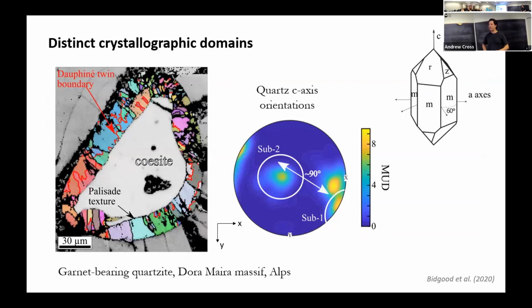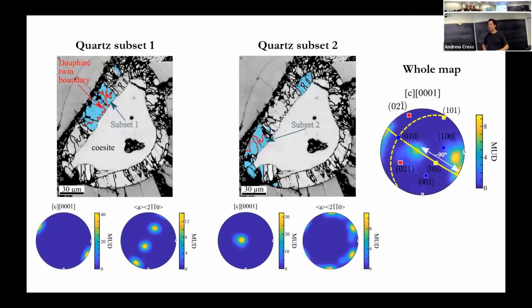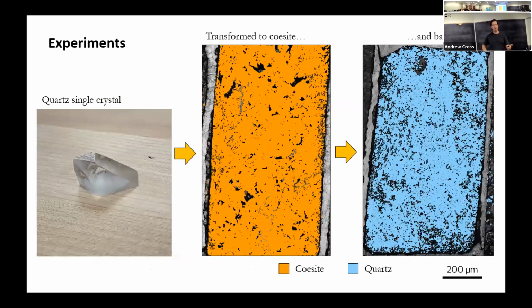If you take one of these samples where we've got a big coesite grain and you look at the quartz around it, you notice if we just look at C-axis orientations, we've got distinct clusters, even though we've got hundreds of grains here. We can look at two particular clusters that are misoriented by about 90 degrees from each other. We can break those out into different subsets, and they're rotated about this axis up here, the rotation axis that fits through those two points. And that corresponds to a shared A-axis in the quartz.